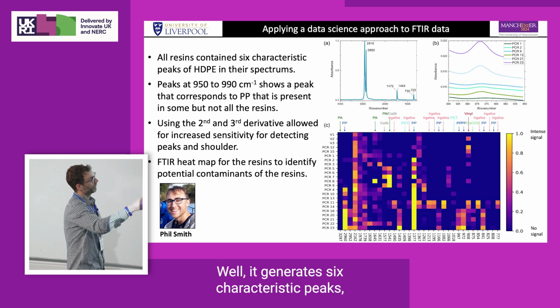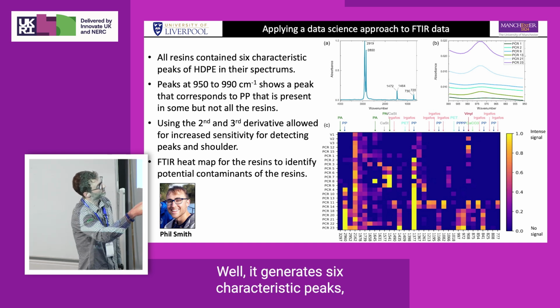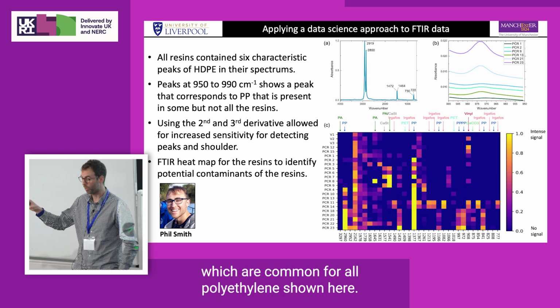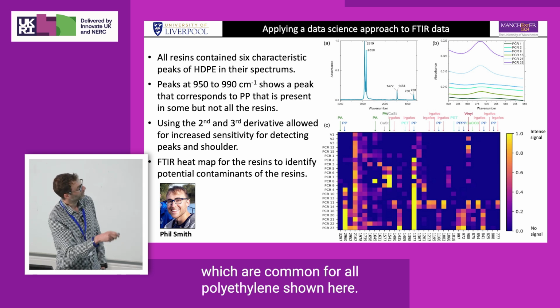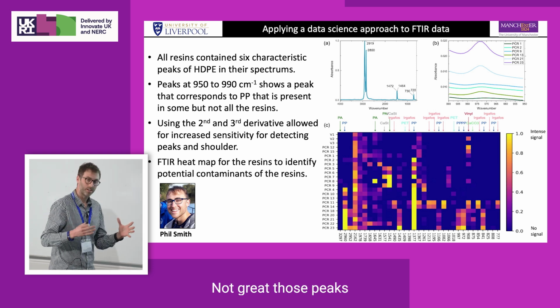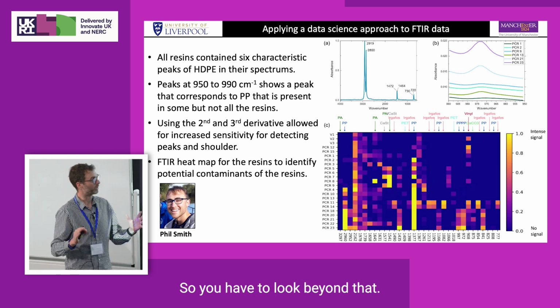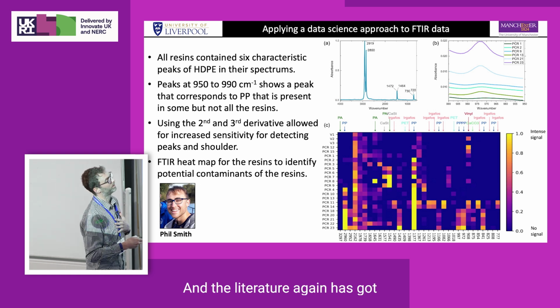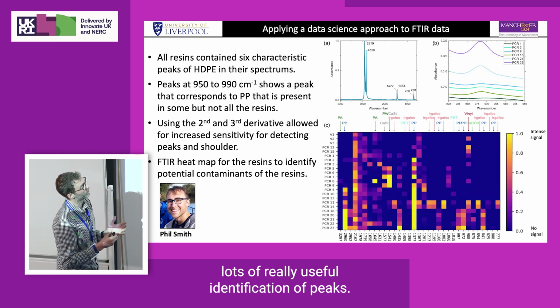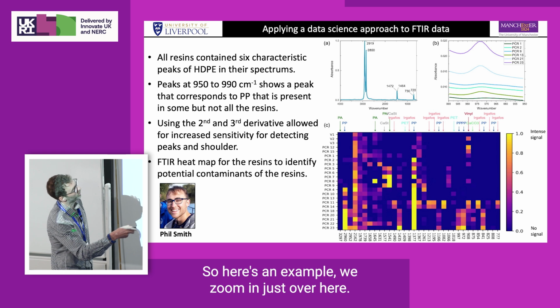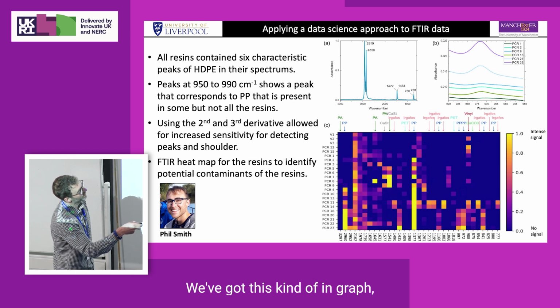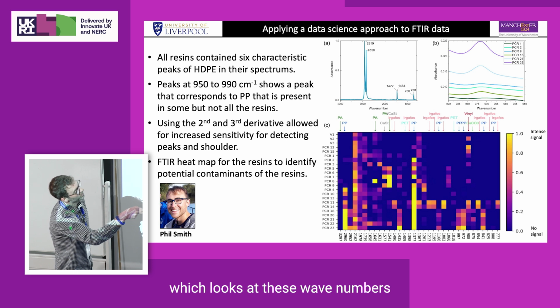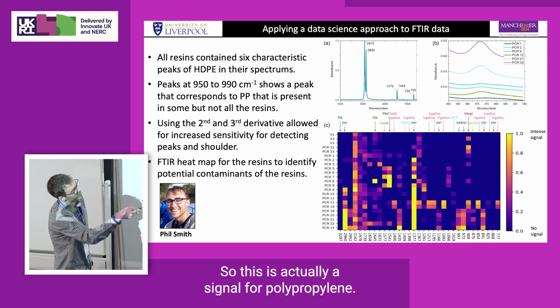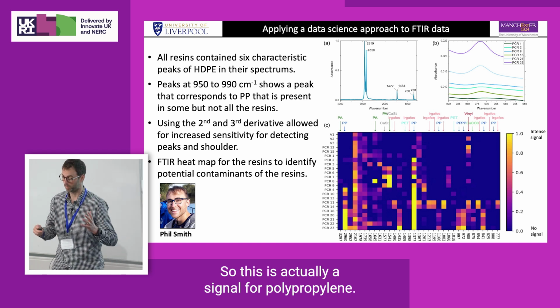So what does that generate? Well, it generates 6 characteristic peaks, which are common for all polyethylene, shown here. Not great, those peaks, in terms of differentiating your sample, so you have to look beyond that. And the literature, again, has lots of really useful identification of peaks. So here's an example. If we zoom in over here, we've got this graph which looks at these wave numbers, and we can see that there's a peak that's different for some samples compared to others. This is actually a signal for polypropylene.